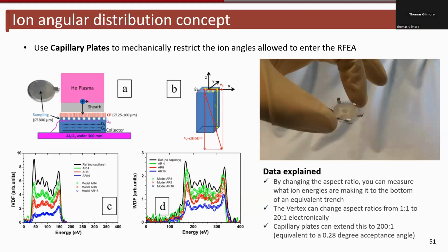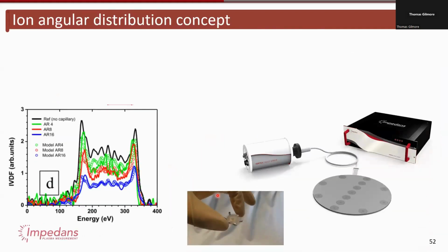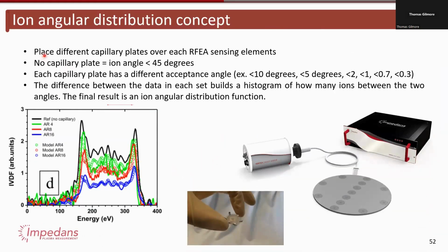So what's the concept to measure the ion angular distribution function from this? The idea is you would place different capillary plates over different sensing elements on one of these arrays. When you have no capillary plate, that's giving you information on ions less than 45 degrees.